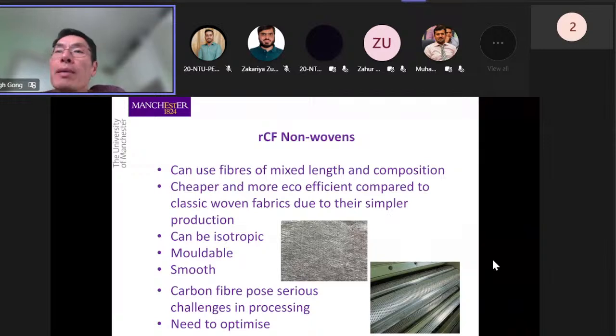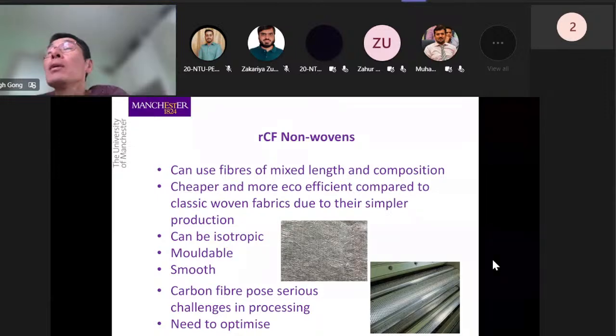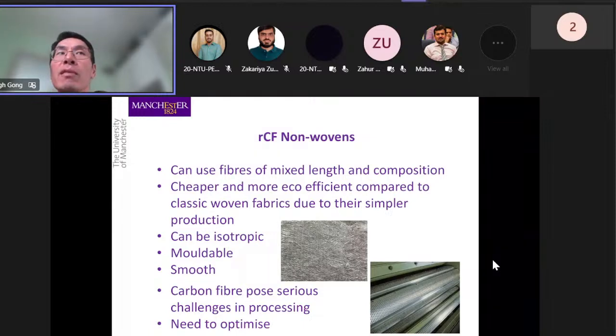when we use carbon fibers in the nonwoven process, there are certain issues we need to be very careful about, because nonwoven processes involve a lot of mechanical opening of the fibers, and you can see some of these in this picture. I think if you are familiar with yarn production in textiles or nonwovens, these are fairly obvious because we need to use lots of sharp wires to open the fibers up. And these mechanical processes can damage the carbon fiber. And more seriously, they can generate a lot of dust material.